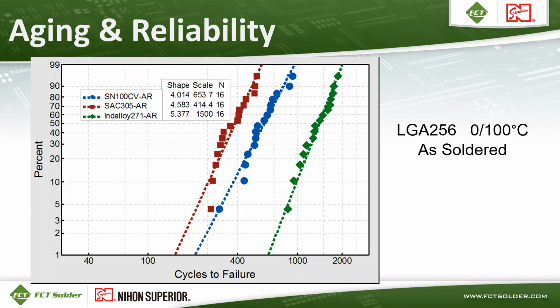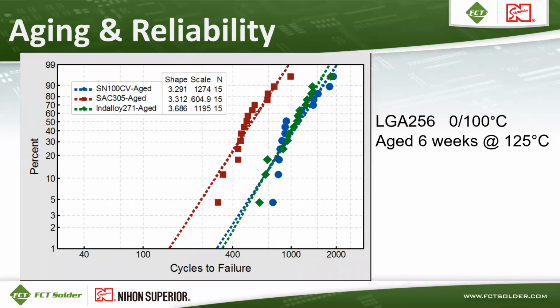So this was aged 6 weeks at 125 C, and the same test was run with the 0 to 100 C thermal cycle range. SAC 305 is still the lowest overall life, but SN100CV and Indaloy 271 now match each other on this particular component after aging. That's because the Indaloy 271 lost some characteristic life because of the particle coarsening effect that's occurring in that alloy.